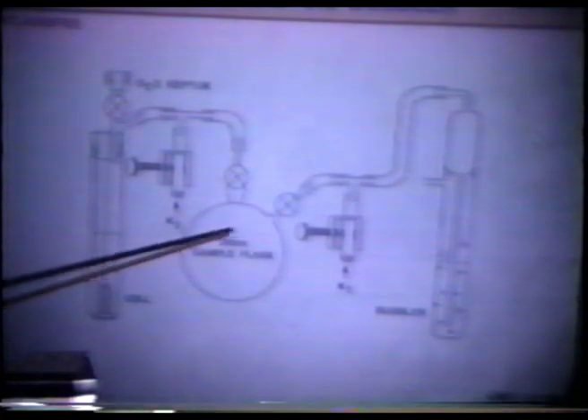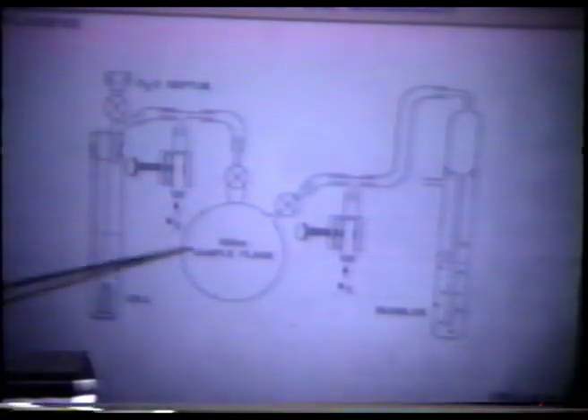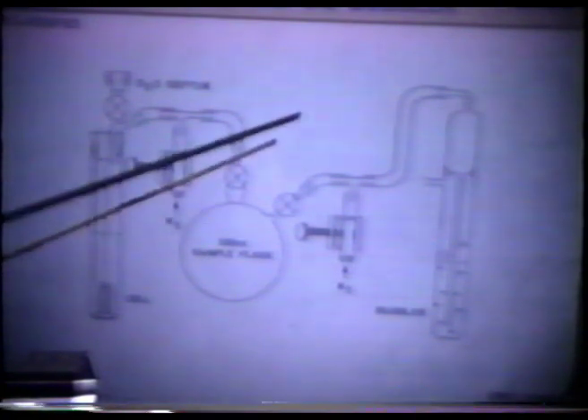Besides that, we would let the flask sit there with gases being evolved for at least 2 days, often much longer. And the rate of electrolysis would be sweeping the gas out about 19 times a day. The amount of gases we were producing by electrolysis would be equivalent to flushing this flask out 19 times per day, in addition to all the other precautions we took in setting it up.